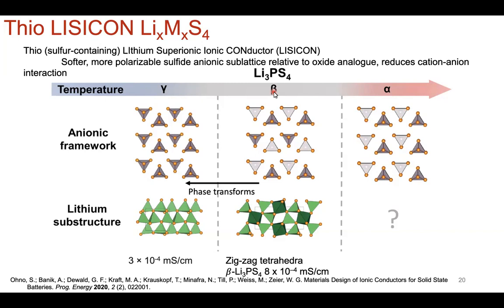Okay, so you react at a high temperature, quench, and basically arrest the product at that particular high temperature phase. You could also go to high pressure if the high pressure phase is also the high temperature phase, which is not always so clear, and that's not always the case, but that is potentially another strategy: to access a phase that is inaccessible under ambient conditions by changing something like pressure.